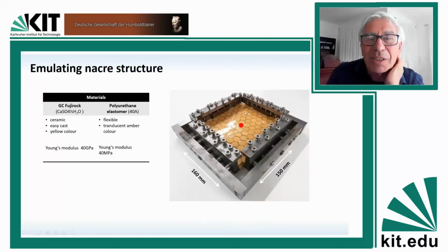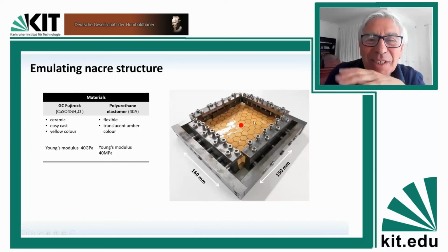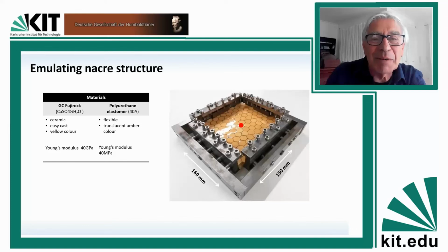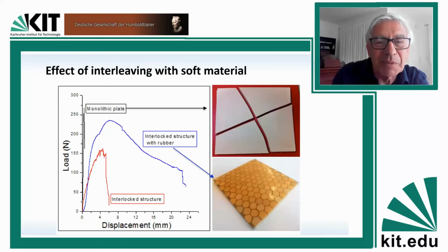Now, our osteomorphic blocks resemble those platelets if we look at the projection from the top of the structure. You can see a similar structure. So we took ceramic osteomorphic blocks, and we also embedded them and/or interleaved them with some resin, with a soft polymer.